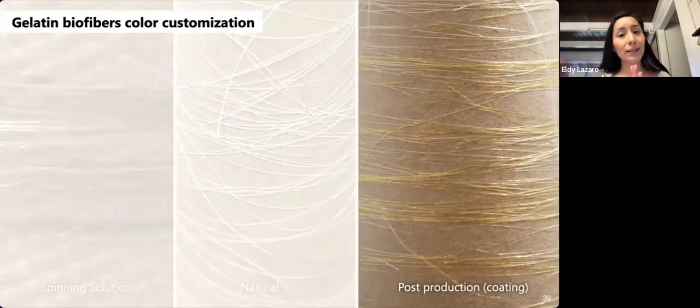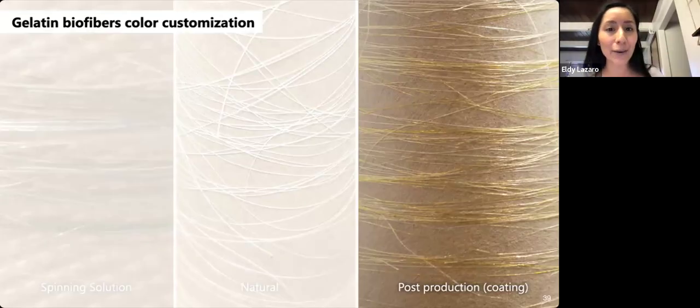So the purpose of the different rollers and baths is that we can customize the fibers as they move along in the drying process. We can add colors. Sometimes we can also make them more elastic by adding a plasticizer, which means something that will make it softer and elastic, such as glycerin.